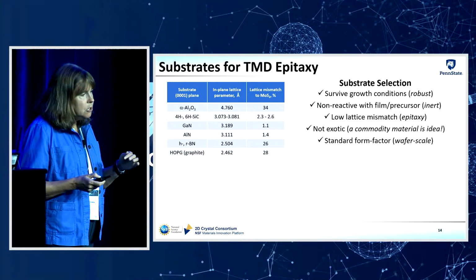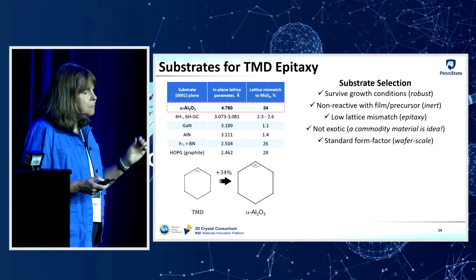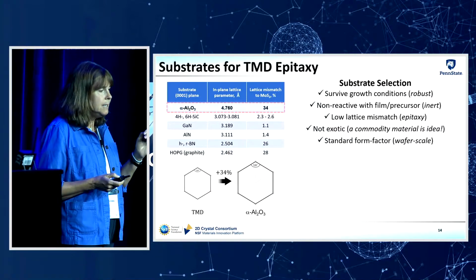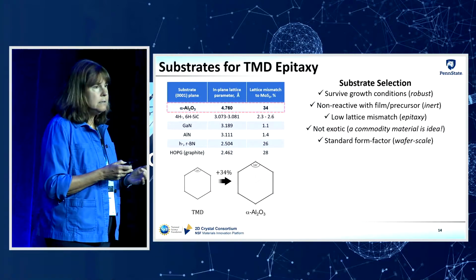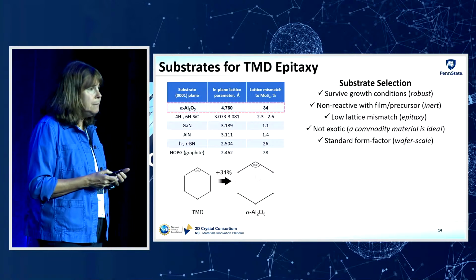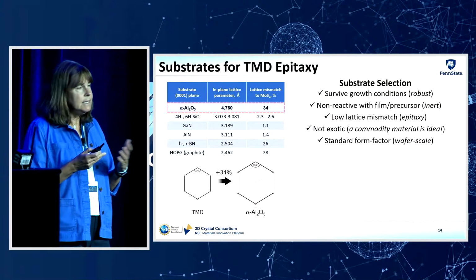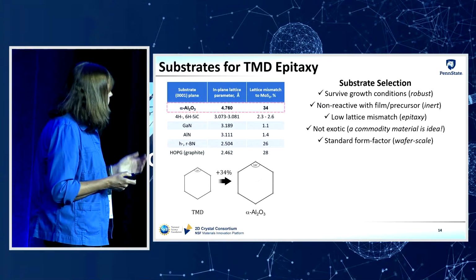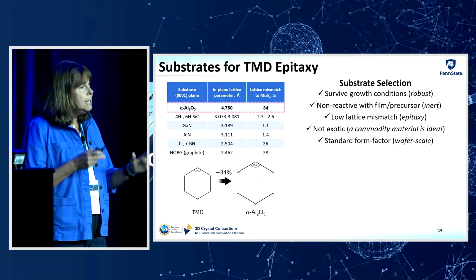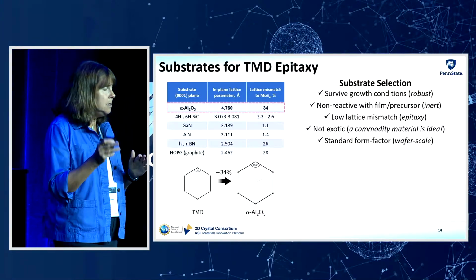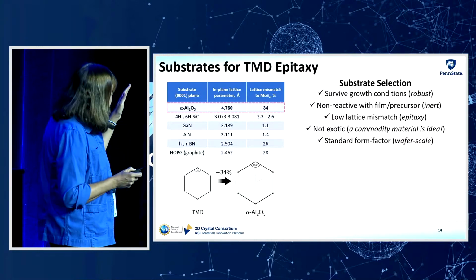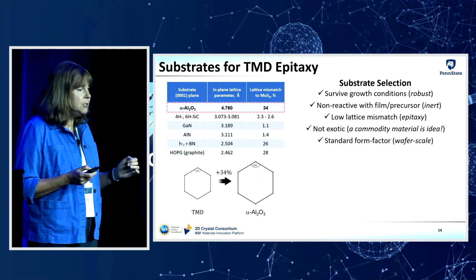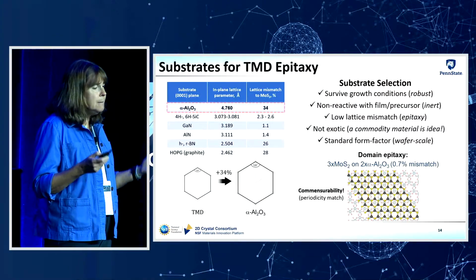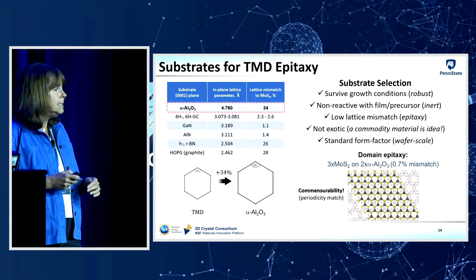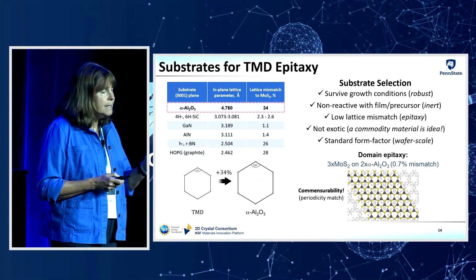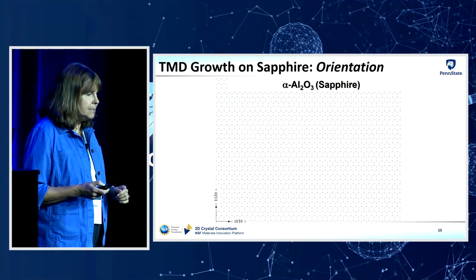Now, there are a variety of different options for substrates for TMD epitaxy. We've focused on using C-plane sapphire, as I mentioned. And the reason for that is that sapphire is very chemically and thermally stable at high temperatures. Also, it has hexagonal symmetry, which is similar to the transition metal dichalcogenides that we're depositing. Now, if you just compare the lattice constants of moly disulfide and sapphire, that would indicate that there is a pretty large lattice mismatch, about 34%. However, there's commensurability between the lattices, and that significantly reduces the effective mismatch. So it makes sapphire a good substrate to use for TMD epitaxy.